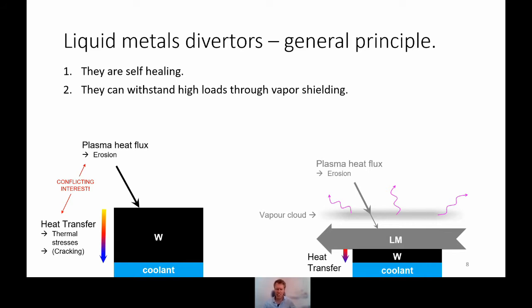For a liquid metal divertor, you can then immediately see why this might be a good idea. The plasma heat flux again erodes some liquid metal, but that's fine because you can have a liquid metal flow and there can be replenishment. And so we have point one, self-healing. The evaporated metal goes into what we call a vapor cloud, but this vapor cloud also acts as a sort of shield, hence the term vapor shielding. Power is dissipated by this cloud because the cloud heats up, the particles are lost elsewhere, or maybe they radiate. And this, we thought, and now we know for sure, can be a very effective way to dissipate heat.